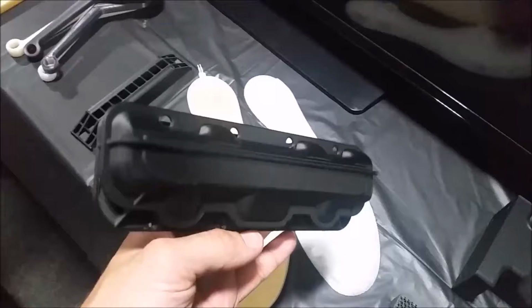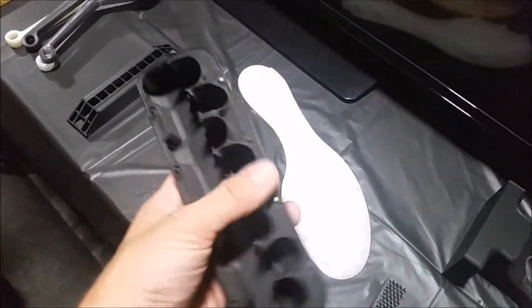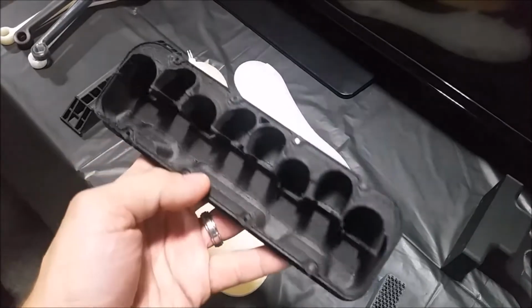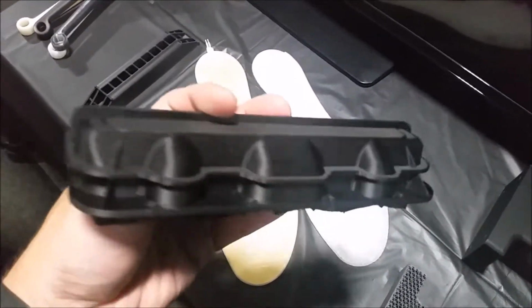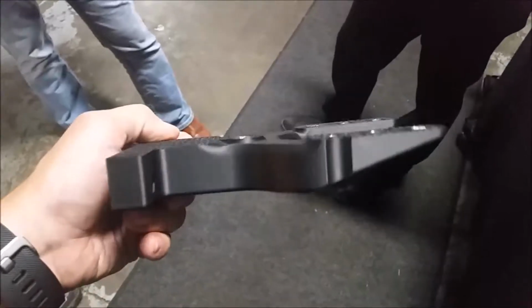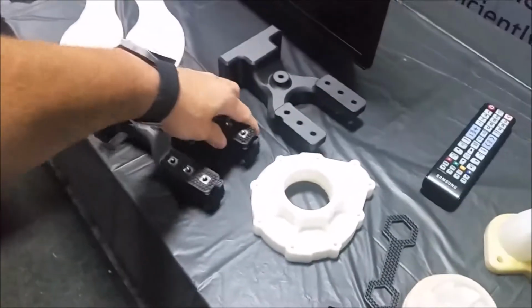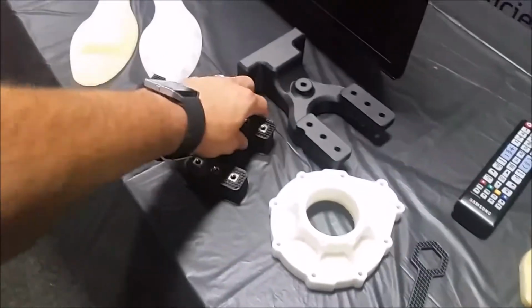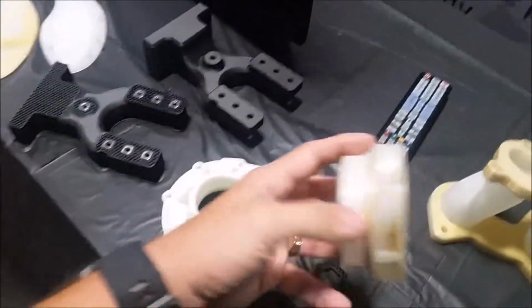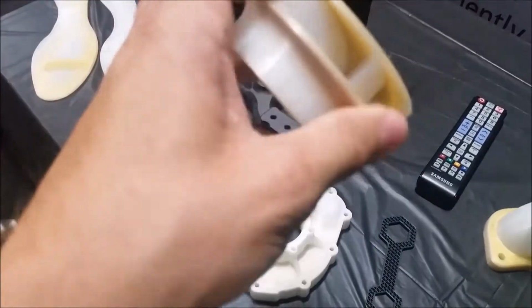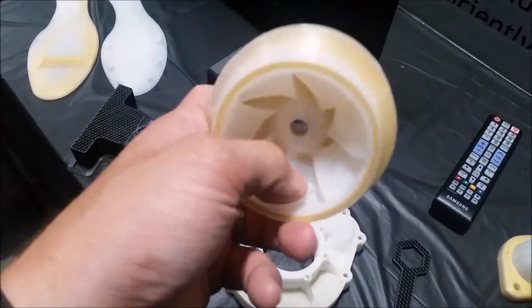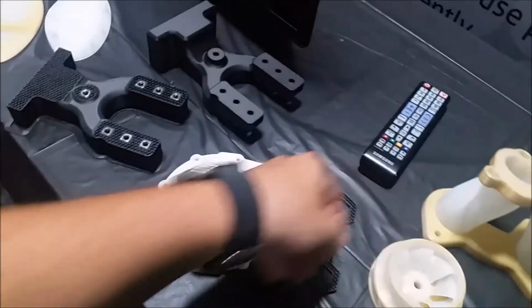How is your pricing compared to others? I'm not going to lie, it's a little bit more, but at the same time, at least from what I've seen out in the market, there are two differentiators in the carbon fiber filaments. One, most of them use chopped carbon fiber as opposed to us using powdered carbon fiber, and the reason that is significant is you get a much smoother blend in the actual filament, so you get better thermal characteristics. And more often than not, when you expose the two filaments to tensile testing, the chopped carbon fiber, because it's not very uniform in the filament, actually performs worse than the base would, where we perform better in tensile testing using powder.